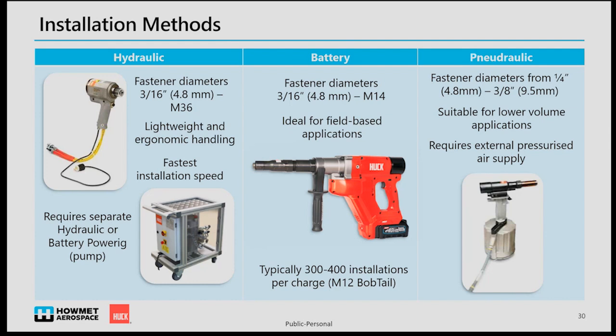Battery tools are, of course, more flexible and easier to use, but due to the high installation load for larger diameters, use is limited to a maximum of 14 millimeter bobtails. So in this case, you can, of course, use the battery tool, but if you have a high number of installations, it might be more efficient to use a hydraulic powered rig. And typically, the battery tool charge is sufficient for 300 up to 400 installations.